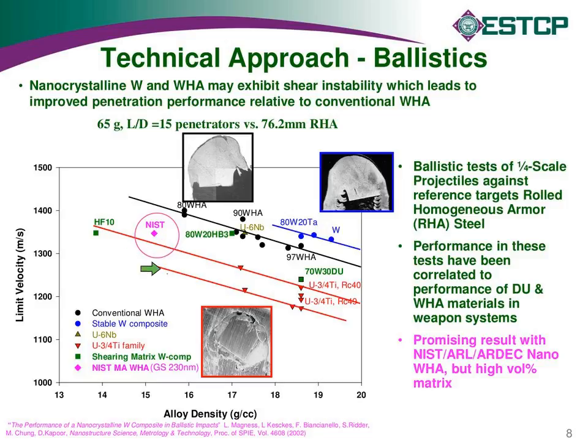It was a relatively low density material, so we weren't quite sure we could attribute all that to the tungsten phase because there was a large volume percentage of matrix in that material. We were about 40% matrix at that point. But you can see its data point is very close to this DU performance line, not the tungsten heavy alloy line. So that was sort of an indication that we should be able to get that behavior if we could get a whole tungsten heavy alloy to behave that way.